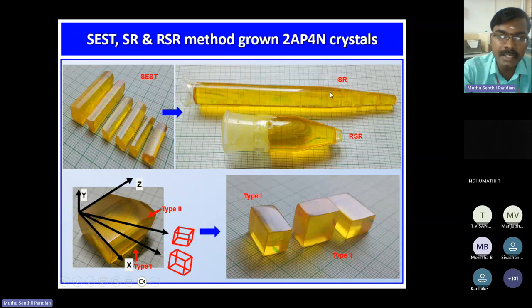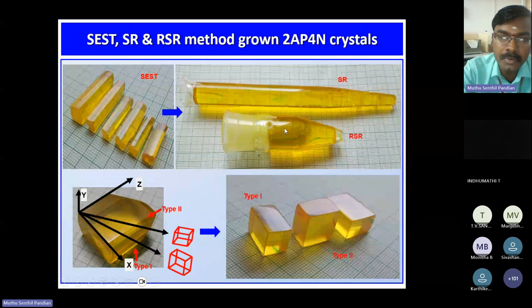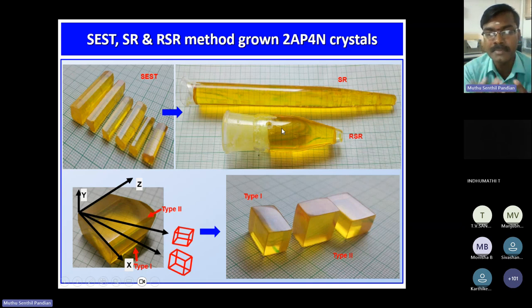The difference between this SR and RSR is that when we grow the crystal by the SR method, due to segregated impurities, we cannot grow further, a maximum of 10-15 centimeters is possible by this SR method. But in order to minimize the impurity segregation in the SR method grown crystal, we have introduced this RSR method. Here, what we have done is we made several holes and slots in the RSR glass sample. So we completely rotate the experimental setup of this RSR method with the seed crystal, with the solution, with the glass sample, everything we rotated so that the impurities are pushed out from the glass sample. One can easily minimize the impurity segregation in the RSR method grown crystal.